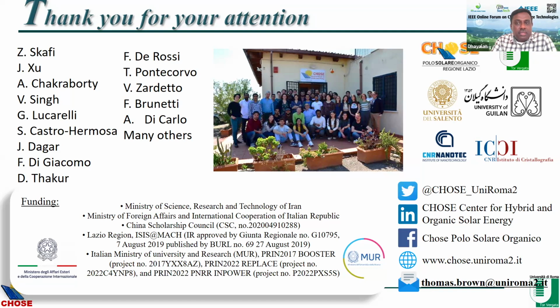And the next question is how would the stability of the perovskite indoors compare to outdoors? Is it the stability in terms of performance? Yeah, that's a very good question. Indoors, the environment is less harsh. There's less temperature variation, less humidity variation. There's hardly any UV because only diffuse sunlight, if any, comes in. So they would be closer to the shelf life test we do compared to the light soaking test we do at 1,000 watt per square meter. So on one hand, they will last longer, which is very interesting for developers of these technologies where stability is an issue outdoors.